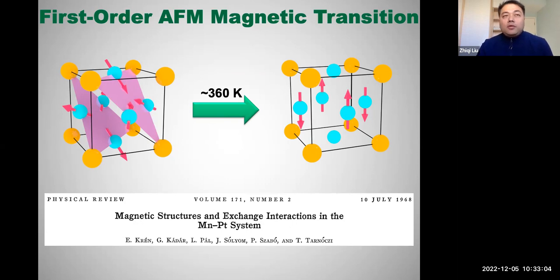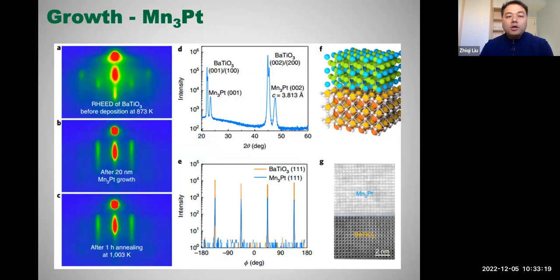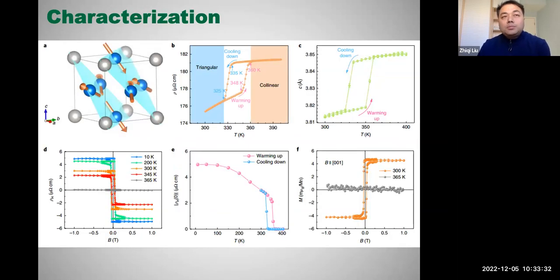So following our experimental experience with iron rhodium, we tried to grow this material on ferroelectric oxides and use a piezoelectric strain to control its different antiferromagnetic phases. For example, we grew this manganese platinum on barium titanate. We got quite nice epitaxial growth. For the electrical characterization, we found a remarkable room temperature anomalous Hall effect for its non-collinear phase, but for its collinear high temperature antiferromagnetic phase, there is no anomalous Hall effect.